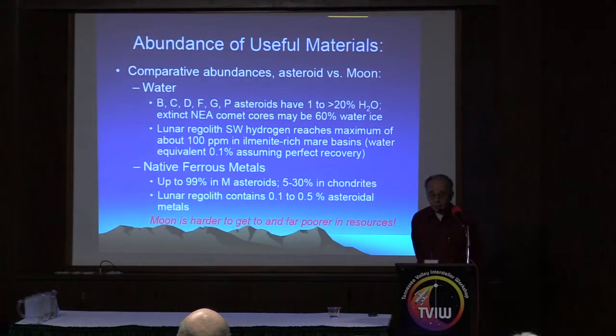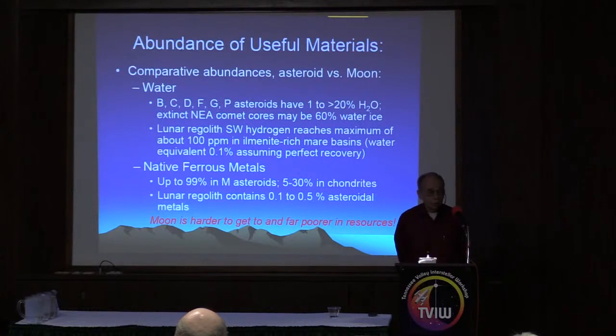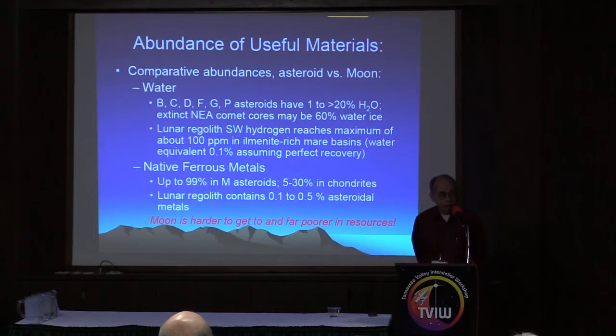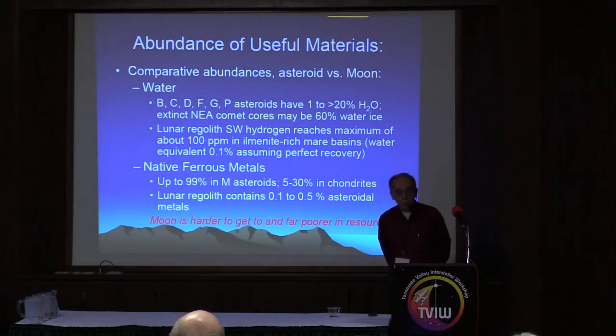The lunar regolith contains about 0.1 to 0.5% of metal, most of which is of asteroidal origin. It is produced by asteroids with poor navigation systems accidentally running into the moon and excavating craters there and diluting the rich metal content of the asteroid impactor with a large amount of lunar slag. And the composition of the lunar surface is, to first approximation, the same as that of the slag that is discarded in metallurgical operations here on Earth. So processes to extract resources from the moon must be imaginative, persistent, and energy intensive.